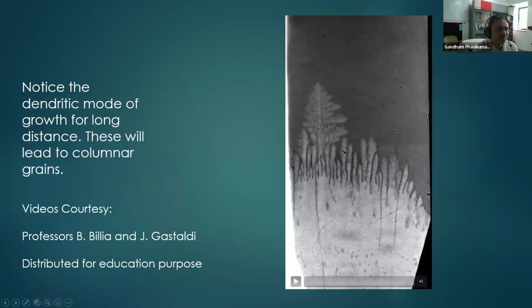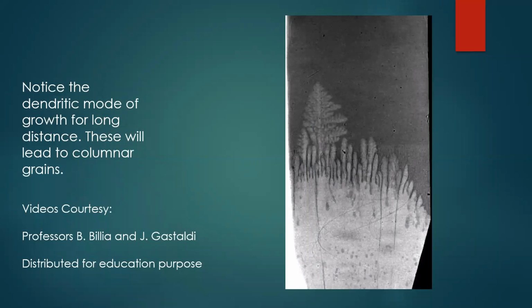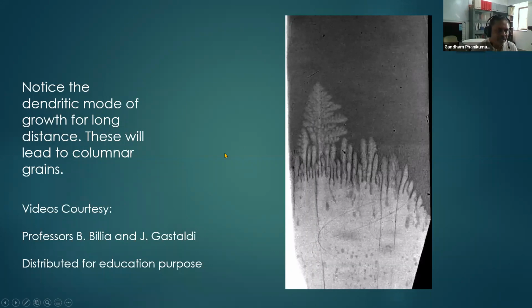Sir, is that mode of solidification possible in pure metals also? So the dendrite formation is possible in pure metals for a particular situation called undercooled melts. Only difference is that it won't matter to us, because even if that pure metal is growing as a dendrite, ultimately the region which is between the dendrites and in the dendrite, it's all the same metal. There is no difference in the composition, and therefore it doesn't matter to us. So that's why we don't need to talk about it. But the concept of dendrite formation is very much applicable even for pure metals, but only in undercooled melts.